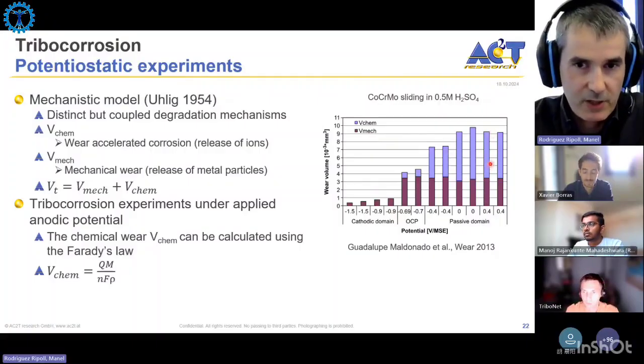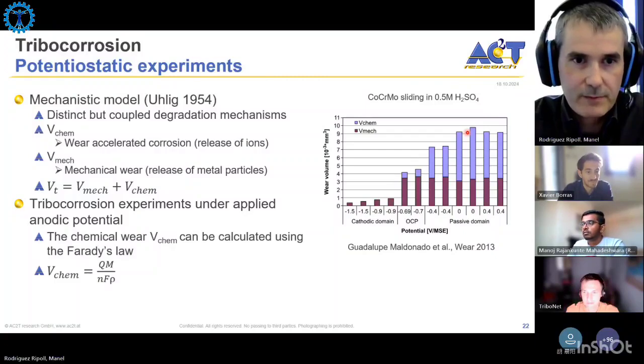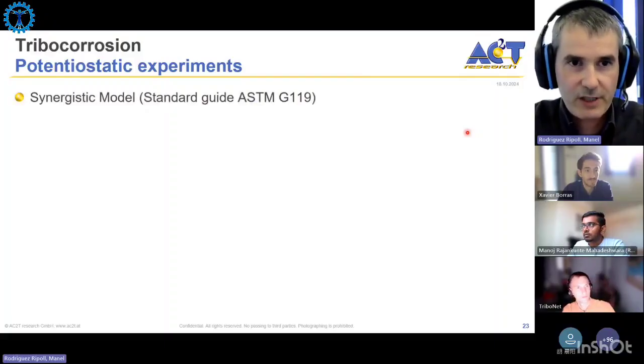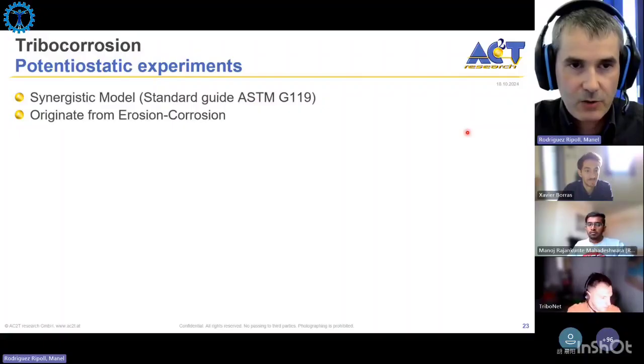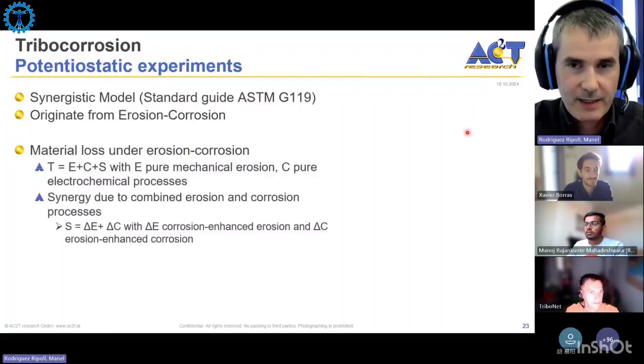And this is something, for example, that you can check for a certain material in a certain electrolyte, and then you can understand how the material is degrading under tribocorrosion conditions as a function of the applied potential in the different electrochemical domains. There is another model that originates from the erosion corrosion community that is called the synergistic model. So this model, the approach is similar, but somehow slightly different.